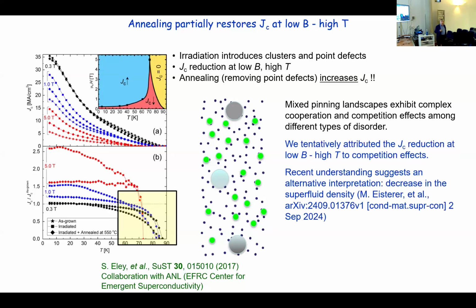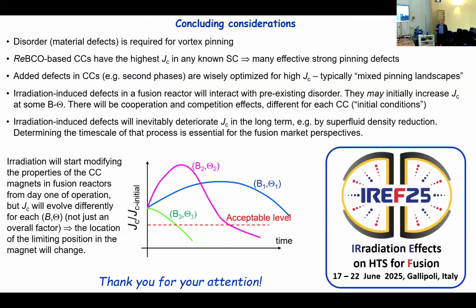At that time, we interpreted that thinking that these mixed pinning landscapes have a lot of interactions between different types of defects. Some of them are cooperative, some of them are competitive. Some combinations of defects are detrimental because they act in opposite directions. We thought that this was some kind of detrimental effect due to competition between the two types of defects. The recent understanding, motivated by the interest in the fusion community, is that this may be simply due to the reduction of the superfluid density. There is a very interesting recent paper by the Vienna group discussing this. So this is an alternative recent interpretation.